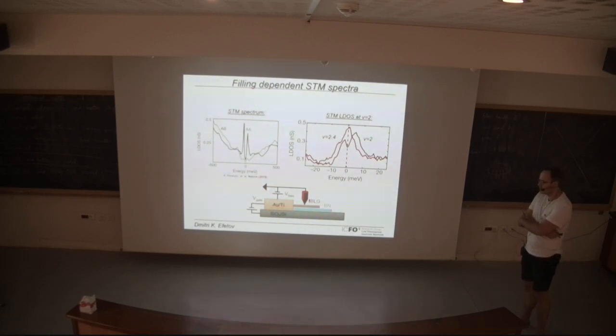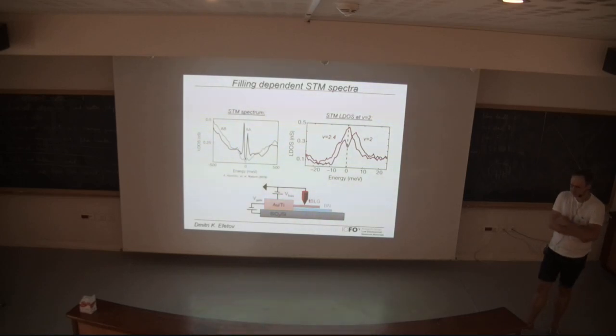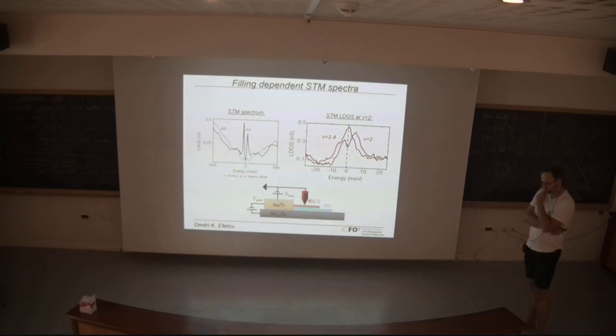Usually when we think of the Mott insulator, for example, we say that the quasi-particle peak that is at the Fermi level goes down, and then you have just the incoherent Hubbard bands. But the incoherent Hubbard bands are essentially localized states, so they are not conducting. They should not be seen as a local density of states in STM if the physics here is also that of the Mott insulator. I'm just wondering how to interpret these.